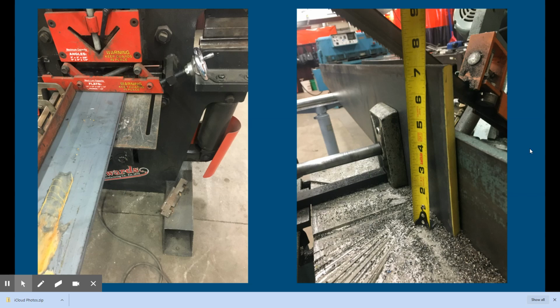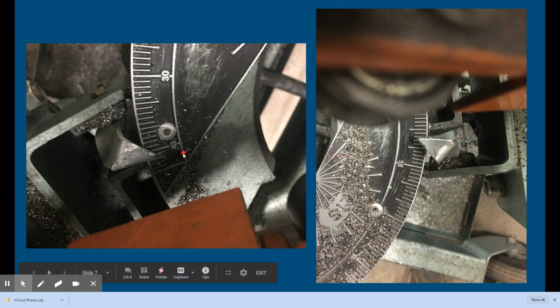I'll have them cut them an inch, 1.5 inch for practice, and they'll have bevels on both sides so that they can just keep putting another piece on the end and another piece on the end, until they practice this joint several times. But more often than not, if they're doing test coupons, I'll have them take it over to the iron worker, and we'll cut out like a 7.5 inch piece. And then we'll set our bandsaw at the correct angle. So 45 if we're doing a single bevel for a 2G, or a 22.5 if we're doing a bevel on each side for the V groove, sorry, the 3G.